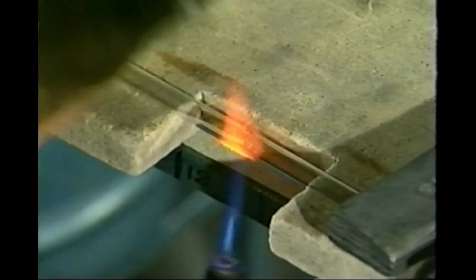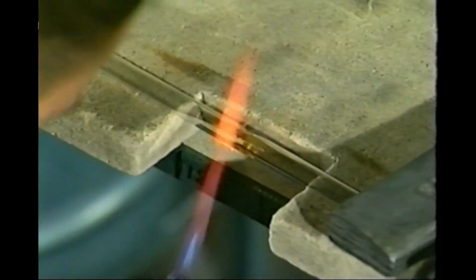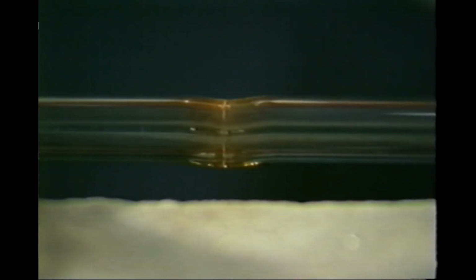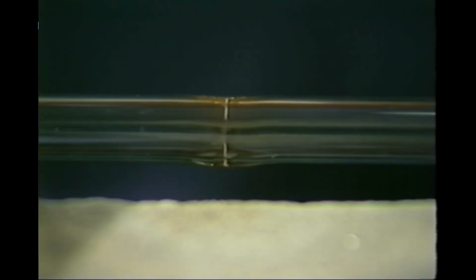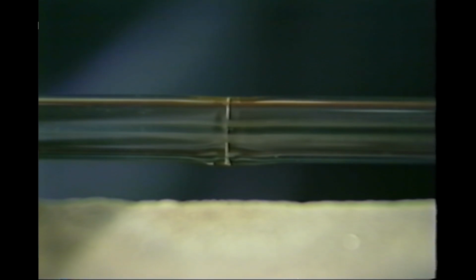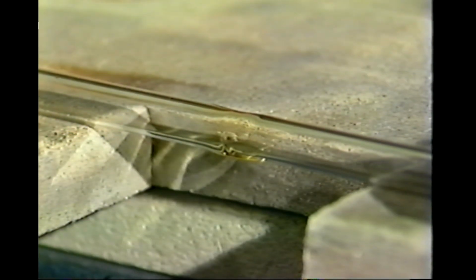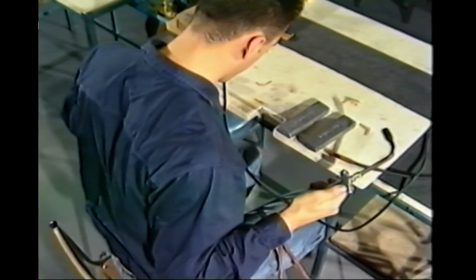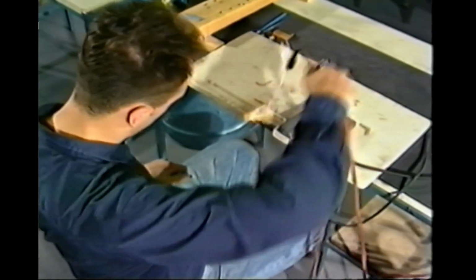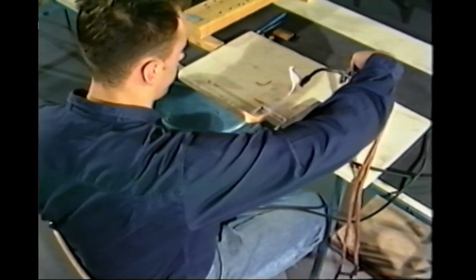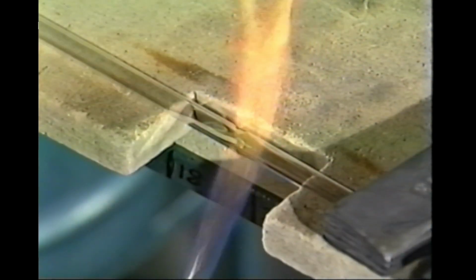Bring the flame to bear on the top of the heated area to achieve the extra melt. Remove the flame and blow gently into the blow tube until the heated area slightly exceeds diameter. Pull back gently on the left-hand tube until tube diameter is restored and the correct wall thickness is achieved. Finally, adjust the hand torch to a large, soft flame and anneal the whole of the heated area and glass up to 15 millimeters either side of it, right around the tube.